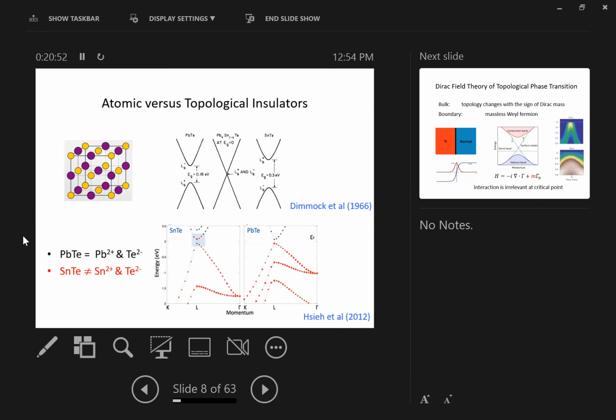Within the framework of band insulators, this actually really happens in real materials. The first example of this kind of gap closing and reopening, the so-called band inversion transition, that I could find is from 1966. It's actually work done at MIT. Back then, people were interested in narrow gap semiconductors for laser applications. These two materials, lead telluride and tin telluride, both have the rock salt structure, an FCC lattice, consisting of a cation atom, lead or tin, and the anion atom, tellurium.